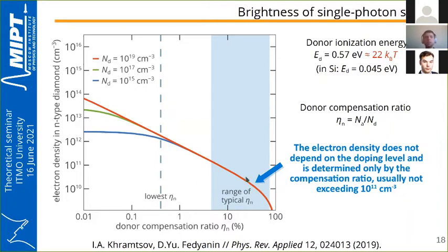If we look at the dependence of the electron density in the N-type diamond on the donor compensation ratio, it can be seen that at typical experimental values of eta n, the electron density doesn't depend on the doping level and is determined mainly only by the compensation ratio, usually not exceeding 10 to the 11 per cubic centimeter.